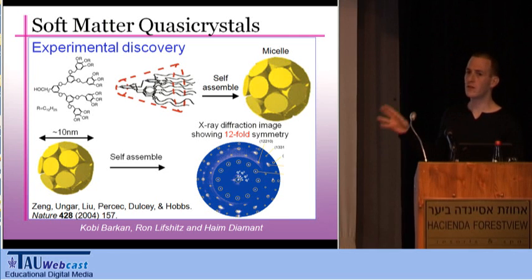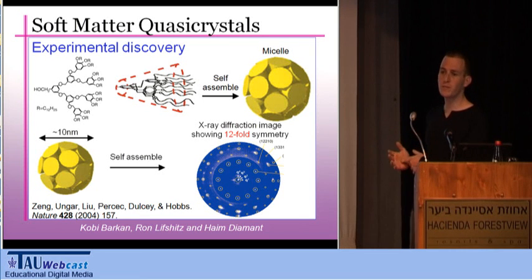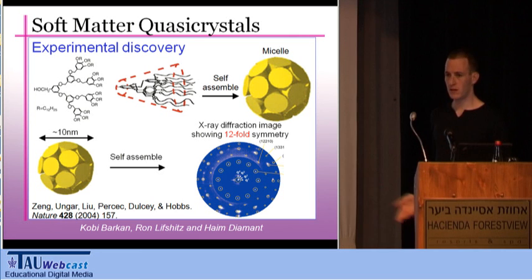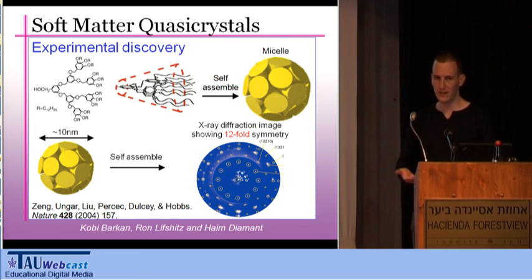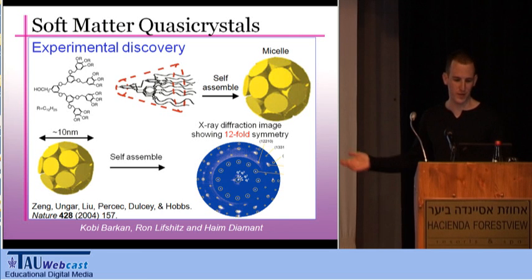They have 12-fold symmetry. And what is 12-fold symmetry? Pretty simple. If you turn the sample 30 degrees, you'll get essentially the same thing. Now, this is impossible in regular crystals. This is the so-called forbidden symmetries. So this is all pretty nice. Again, they got Nature. But why is this happening? How can we explain this? Why didn't they get just the regular liquid crystals as everybody else?